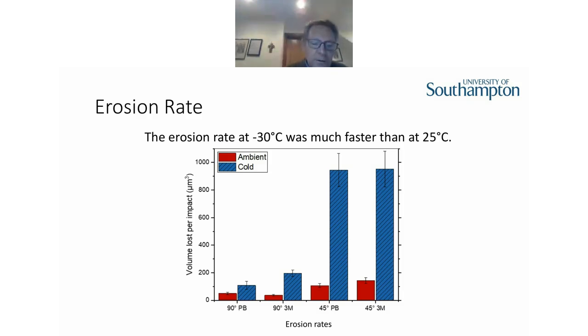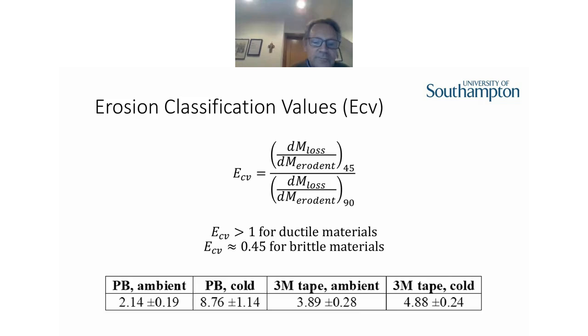As I say, we measure the mass loss, convert that to a volume loss, and then we know how many particles impinge. This is quite a large sample area, so most particles will impinge onto the surface, so you can get a volume loss per impact of sand, and that's in cubic microns, a very small volume loss per impact. Then you can look at this ratio, the difference between the erosion rate at 45 degrees and at 90, which tells you whether you've got a ductile system or not. If this ratio is above 1, then it's ductile. If it's below 1, or around 0.5, it's brittle.